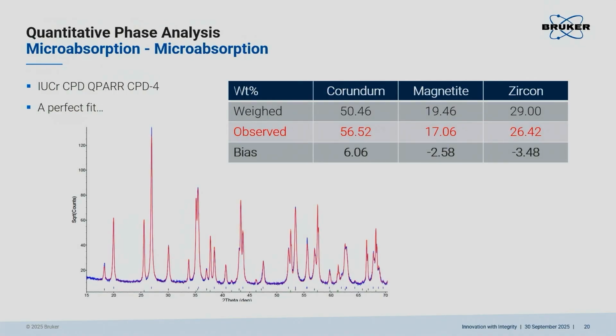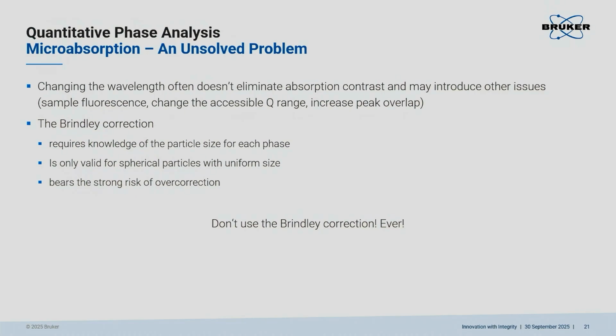That's something people normally do not want to hear, but we're automatically coming back to the good old traditional single peak methods. Yeah, we have to do calibration series. Now, for 2 or 3 phases, to do a calibration series is manageable from time to time. For a 10-phase sample, forget it. So changing the wavelengths often doesn't eliminate absorption contrast, but it may introduce other issues. Changing the wavelength, for example, can give you sample fluorescence. So this is something you want to keep in mind.